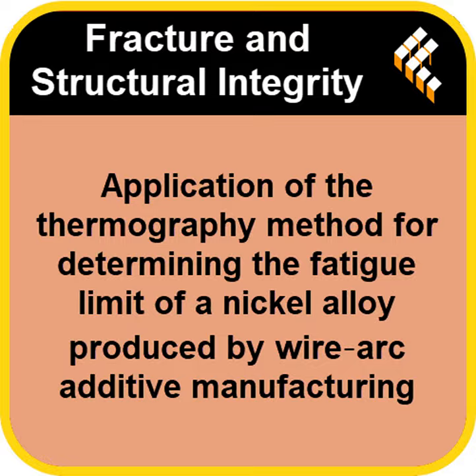Okay, so we know the science, but the key word here is accelerated. If they ran the test for hours, it kind of defeats the purpose. How did they speed it all up? That all comes down to the testing strategy. They use something called block cyclic loading. This isn't one long, continuous test until the part breaks. Right, you said it's more like a series of short sprints.